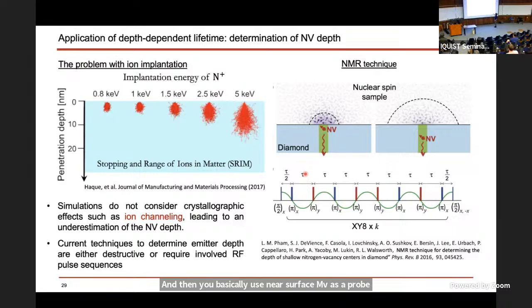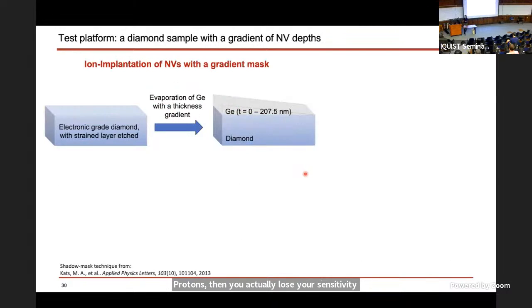But this is a very short-range effect, right? As your emitter gets farther and farther away from these protons, you lose your sensitivity. So what we want to do, in the theme of all-optical techniques, is see if just by measuring radiative lifetime, we can get this information about the depth.